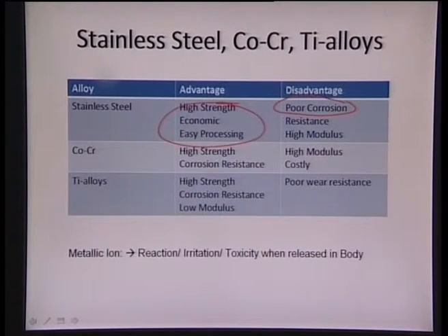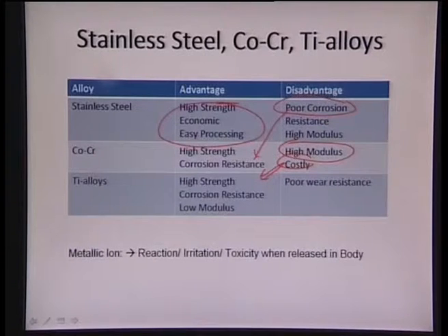So that's the reason we went on to the cobalt chromium alloys, and there we realized that it has very good strength and high corrosion resistance, but the problem is it is very costly and still has very high modulus. If a material has very high modulus, then the bone will start thinking, I don't need to be here, and it will start getting reabsorbed into the body. So that is the reason we want to come back to a material which has a little lower modulus, and that is being satisfied by titanium alloys. They provide a good combination of high strength, good corrosion resistance, and low modulus.